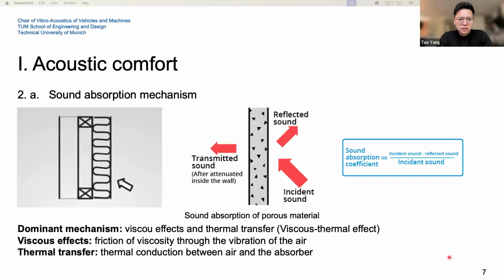applications. I think in some papers or publications, people are still confused about the sound absorption mechanism. It's mainly due to the viscous and thermal effects. The viscous effect is the friction between the air and the pore walls or fiber walls due to the air viscosity. And the thermal conduction is the thermal energy transfer between air and the absorber. Of these two effects, the viscous effect is the dominant one in most cases. I think the viscous effect contributes more than 80 or 90% of the sound absorption.